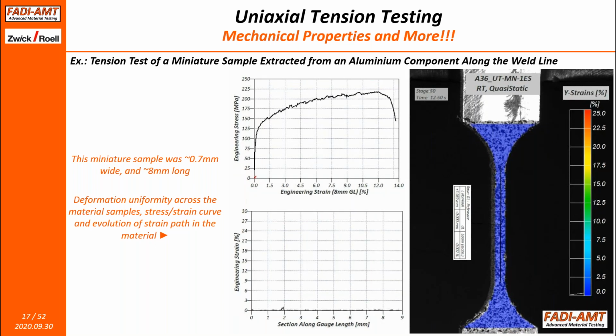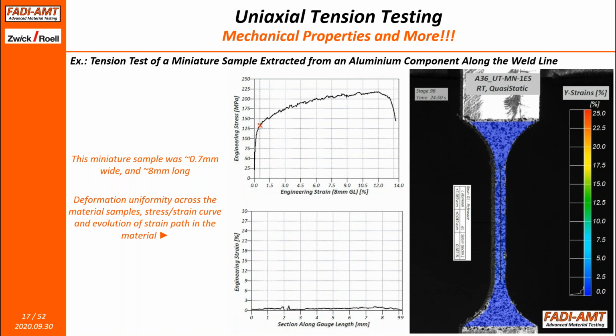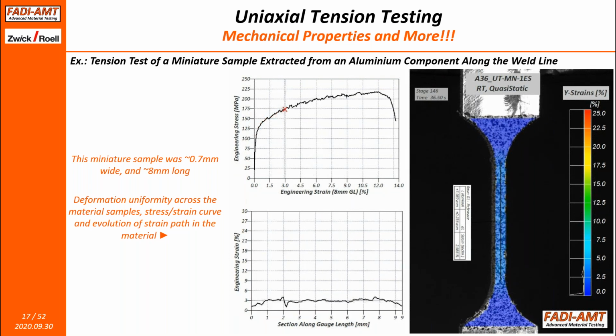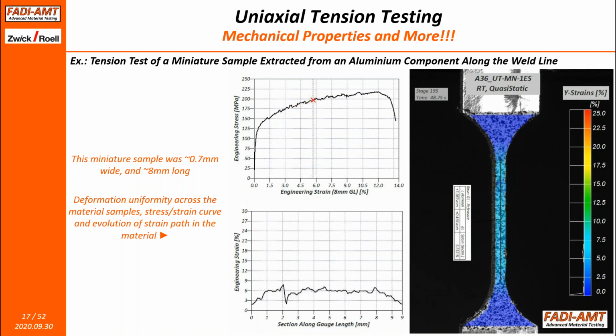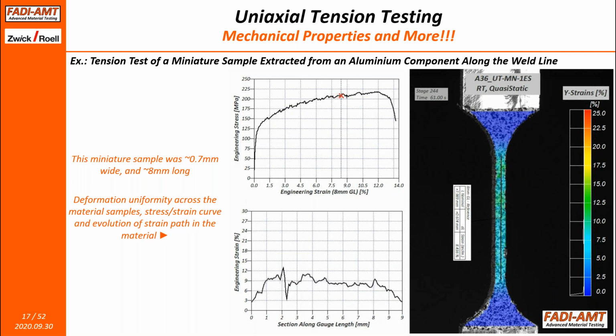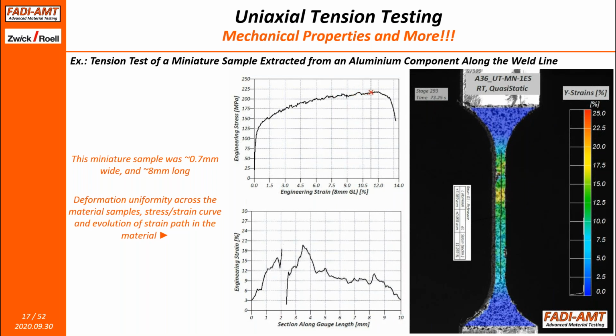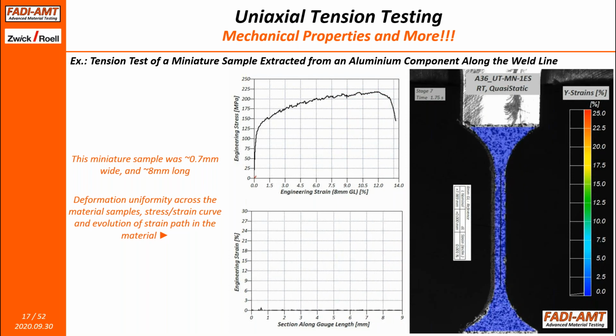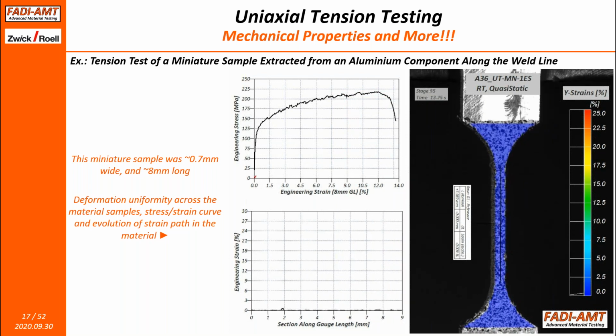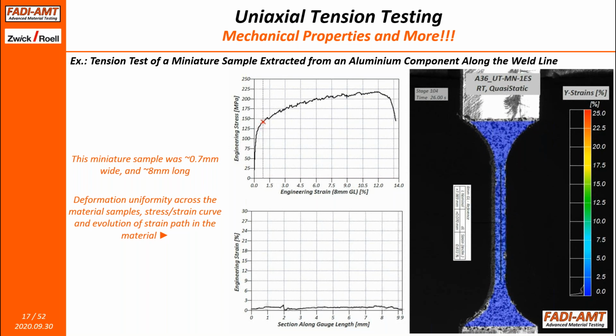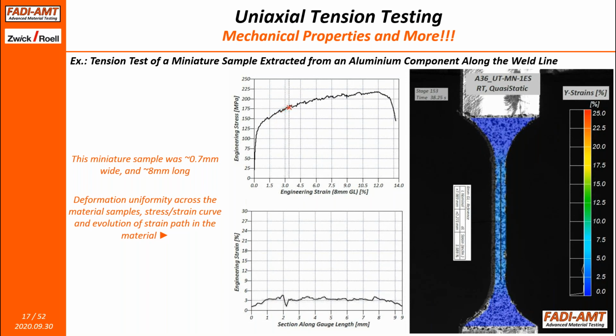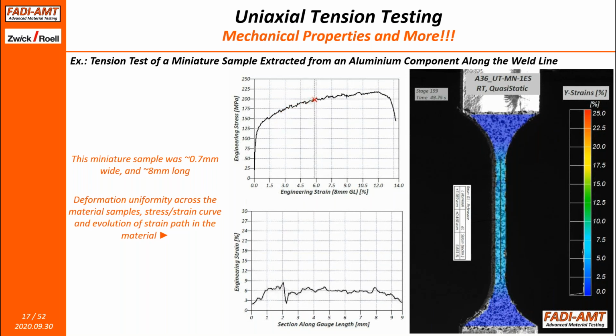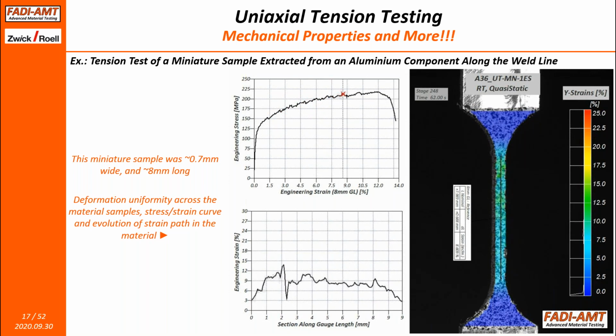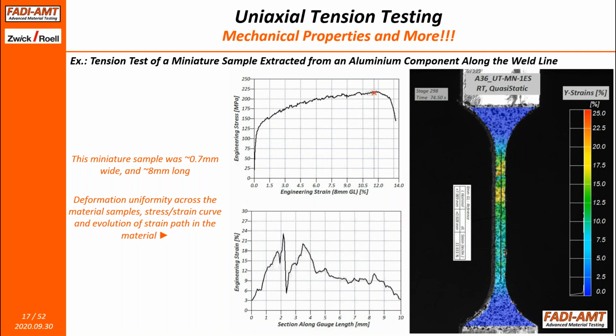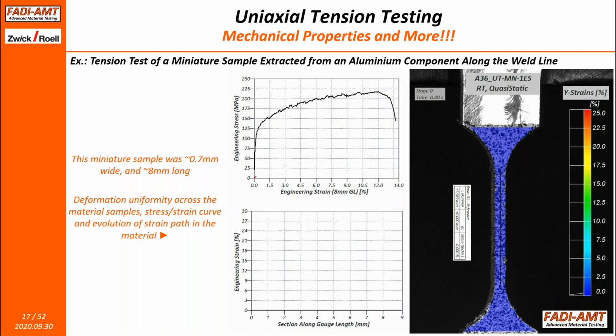Now we go to another extreme. This is an example of an extremity in the sample size where we have to go to the miniature sample size. And this is a weld line, basically. A sample was extracted along the weld line. This is a laser welded aluminum sort of component. And we extracted the sample along the weld line. It was about 0.7 millimeters wide and about 8 millimeters long. This is where, again, could you use conventional or non-contact extensometry? Potentially, yes, I would say very difficult. And so that's where DIC offers a significant advantage in terms of identifying the true behavior of the weld material and also how does it deform.